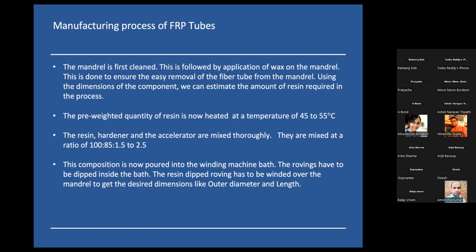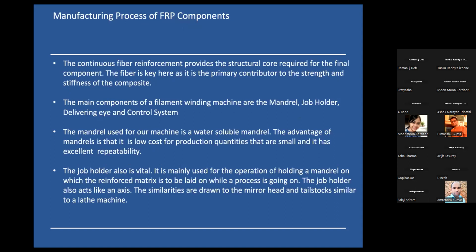The resin, hardener and accelerator are mixed thoroughly at a ratio of, for example, 100 to 85 to 1.5 to 2.5. This mixing ratio depends on the type of resin which we normally use, and it can also vary depending on the resin system we adopt. The composition is now poured into a winding machine bath. The rovings have to be dipped inside the bath. The resin-dipped rovings have to be wound around the mandrel to get the desired dimensions, like the outer diameter and length.